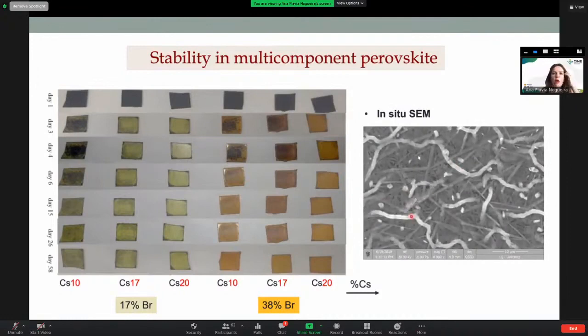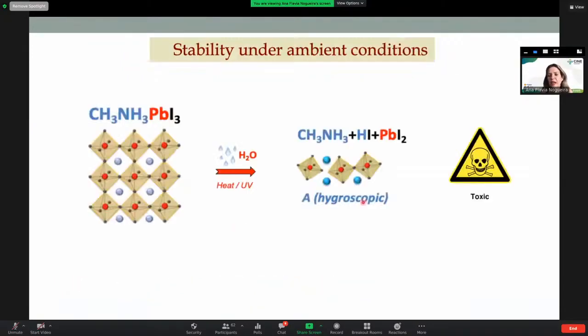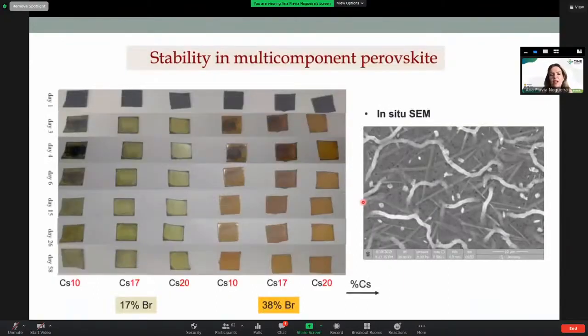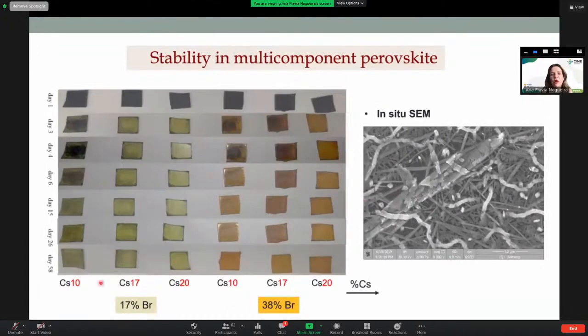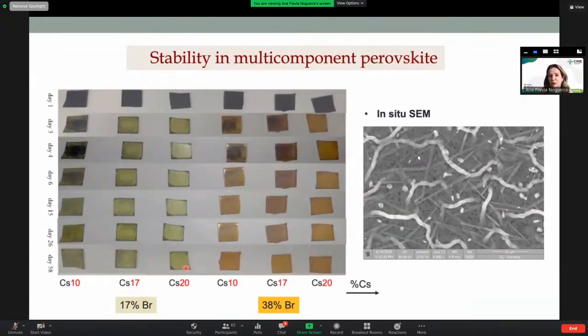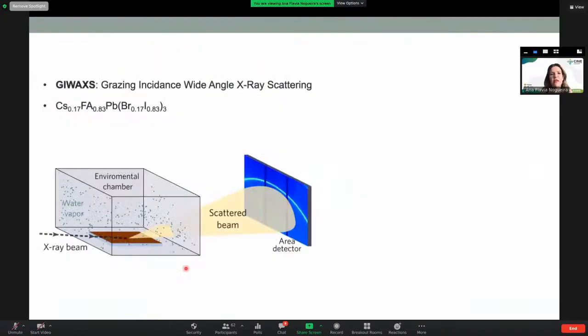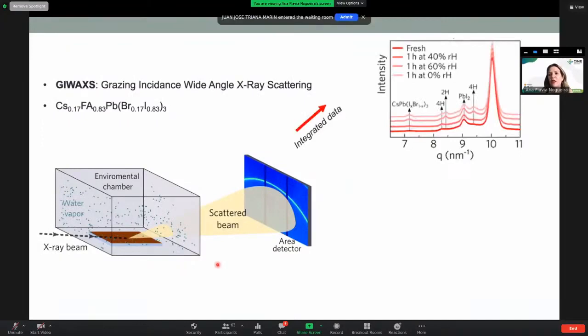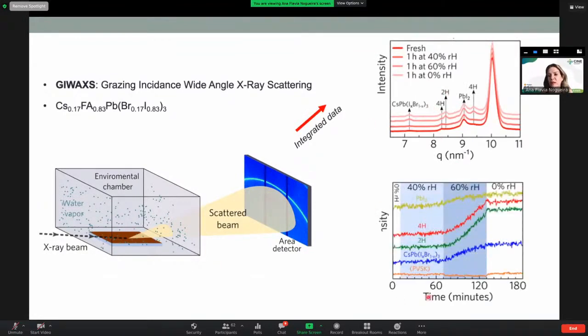We are very interested in understanding the degradation products, because with MAPI, the only product is lead iodide. But when you have these multi-cations, you can see by the different colors that the products are different. So let me pass very quickly to this. We also went to the synchrotron, and you also observe the formation of these hexagonal phases during the degradation. When you plot intensity with time, we see the increase in the signal of these hexagonal phases with time. So it's all about this kind of microrod.